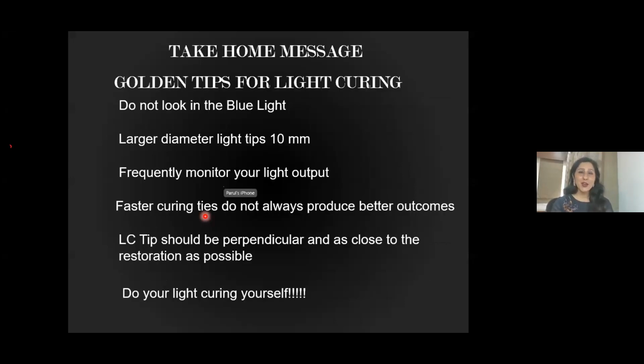So golden tips for light curing: do not look into the blue light. You know, friends, I was amazed when I read an article that if you look 7 times in a day, you know, when we place our blue light, sometimes the light shield is not properly placed and somehow you look at the blue light. If you look at the blue light just 7 times in a day, that is enough to cause degeneration and retinal damage. So if this is really true, then please do wear protective eyewear, and also keep the shield of the light in a proper direction and then start the light curing.